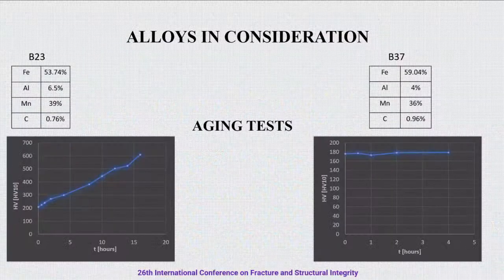For this research, we considered two kinds of alloys named B23 and B37. B23 has a higher percentage of manganese and aluminium, while B37 has a lower quantity of manganese and aluminium. The first test that we did was an aging test at 550 degrees Celsius. From both the graphs, we can see that after 16 hours or so of aging, B23 shows a drastic change in its hardness, while B37 has more or less the same hardness levels.